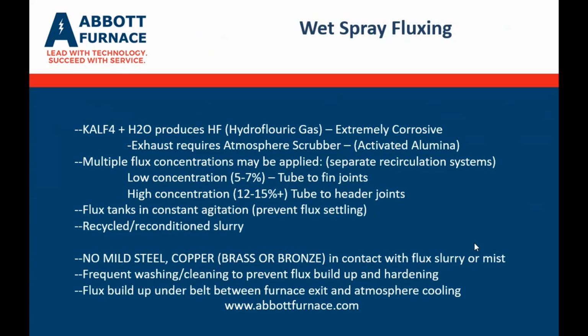In some cases, you may require multiple flux concentrations for parts, such as a low concentration on your tube to fin joints of maybe 5 to 7%. And you can be using a higher concentration of flux on the tube to header or the bigger, thicker joints, say 12 to 15%, but it can be much higher. In a recent case a couple weeks ago, we saw where their concentration was around 30 or 33%. So the fluxer itself can be designed to have both of these concentrations applied automatically, depending on the design and what the requirements are for this process.